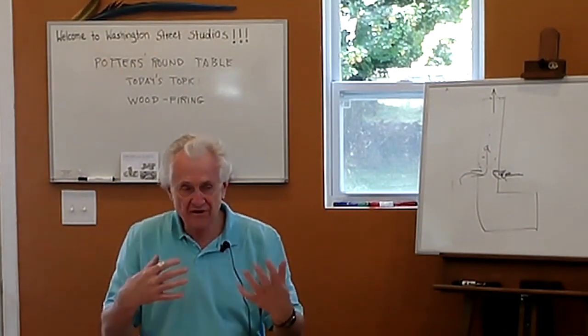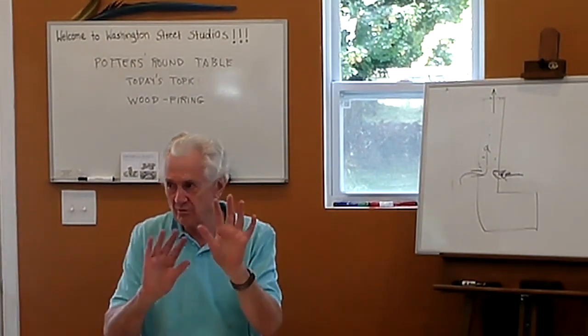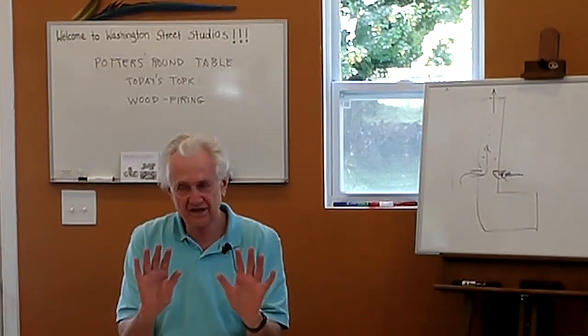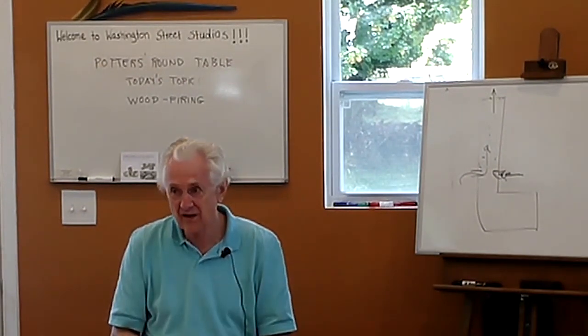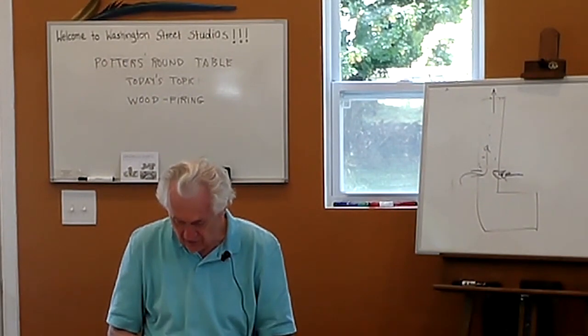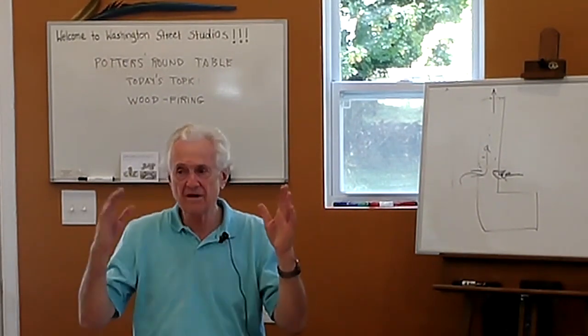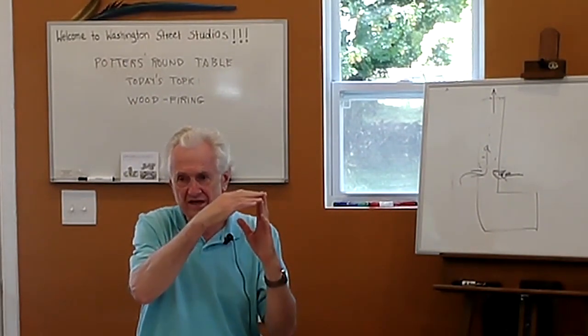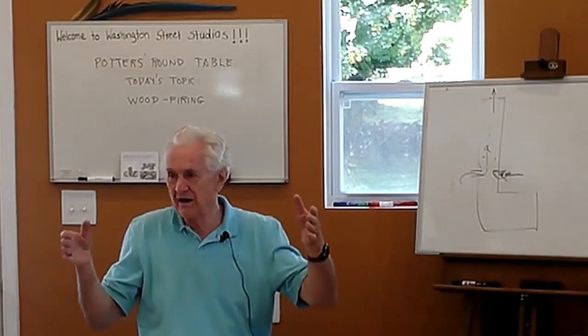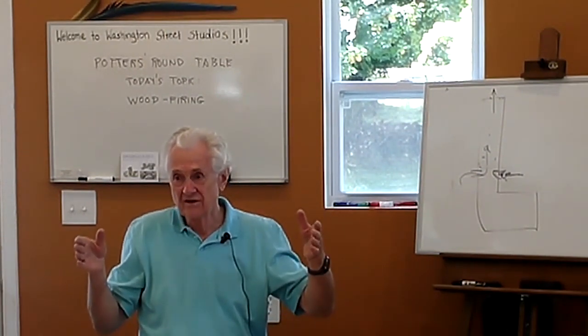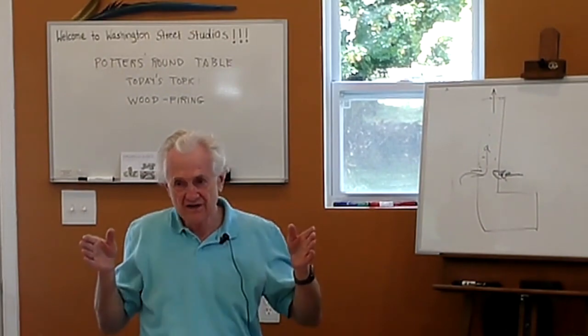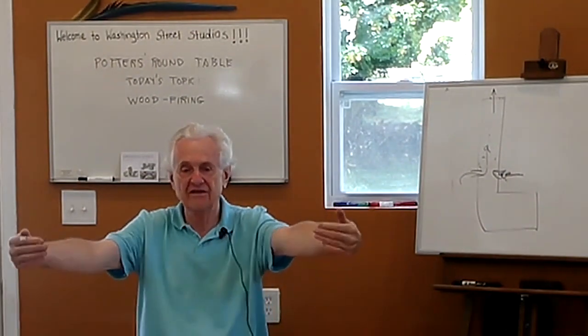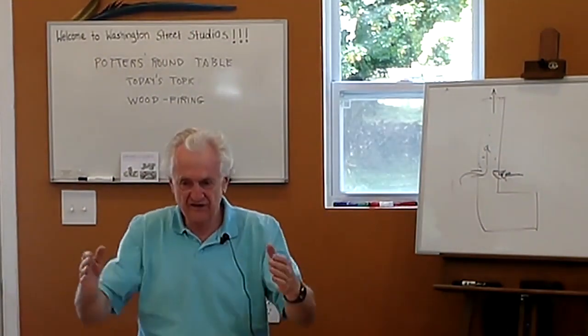So how you direct the flame with stacking or with fake partial walls and barriers inside the kiln, you can sometimes counteract some of these natural hot and cold spots. As I mentioned, if you have square corners on a kiln, square corners tend to be cold spots because they tend to be dead spots. So anywhere you've got a square corner, the flame does not want to go all the way in and then turn and then go out. It'll just skirt the corner.